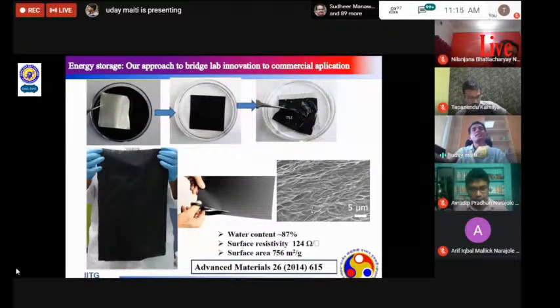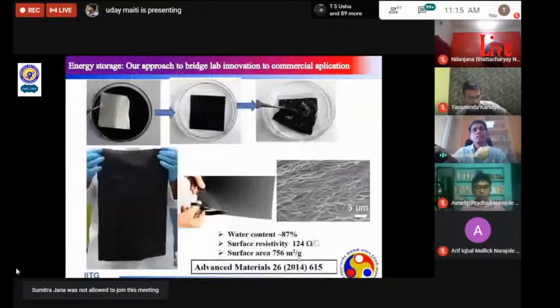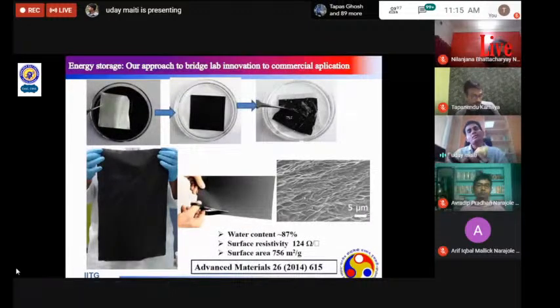And this is very simple. We started with a metal plate, just dipped into the dispersion of graphene oxides. If you want to know the very detail, you can follow the reference which we have published here. You can see from this SEM image, where this is written as 5 micron, the individual graphene sheets, and there are many pores in between. That means there is no complete restacking of the graphene.